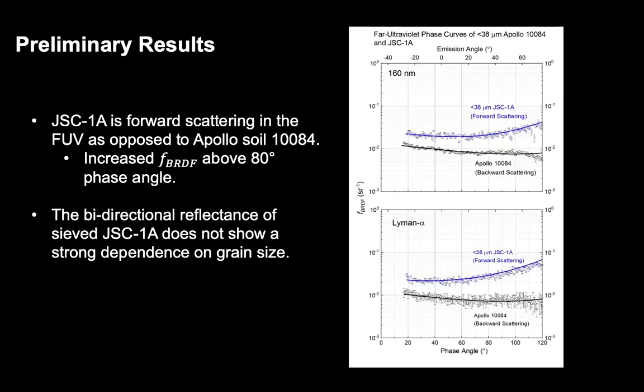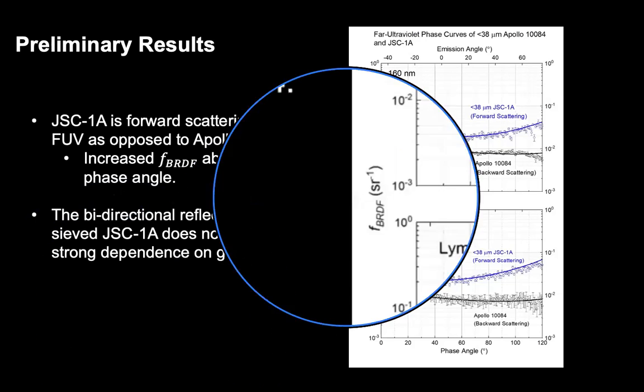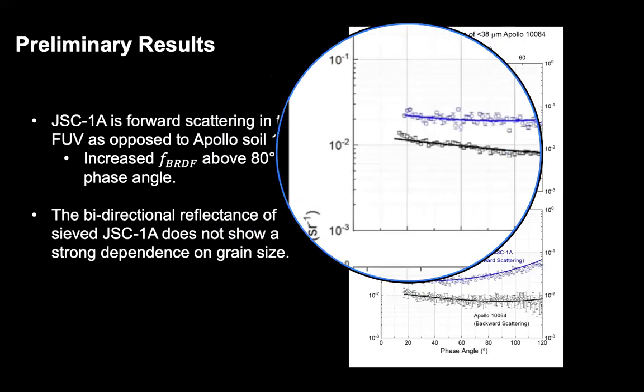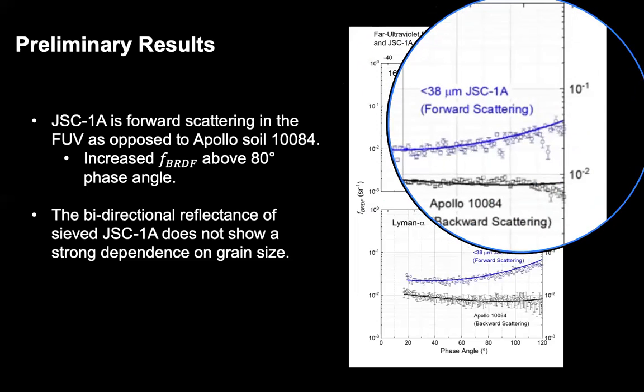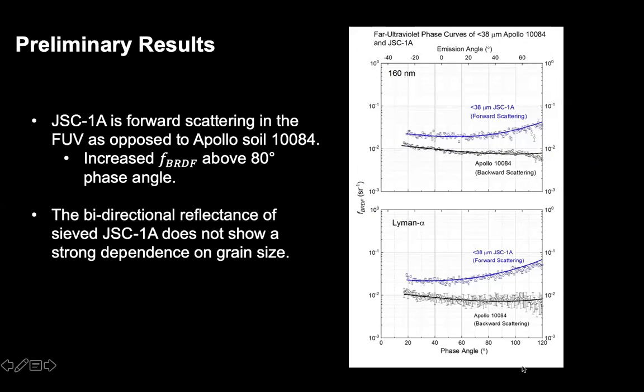So the preliminary immediate results are that the JSC1A actually does behave very, very differently from Apollo 10084 in ultraviolet reflectance measurements. The Apollo 10084 is backward scattering. All right, so that means that as you move away from the incident light, the reflected intensity becomes dimmer as you start to move angularly away from that incident angle. Whereas JSC1A appears to be more forward scattering. In other words, JSC1A acts more like a really fuzzy mirror. It reflects light at an angle away from the incident, which is rather interesting.